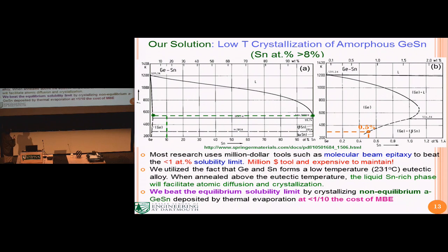And also, you worry about this equilibrium solubility limit. If you want to break those kinds of limits, you should enter a regime where the basic assumption of this phase diagram doesn't hold. All phase diagrams are based on the assumption of thermal equilibrium. If you go to a non-equilibrium state, then you have a chance to break that limit. So we actually beat this equilibrium solubility limit by crystallizing non-equilibrium amorphous germanium tin on dielectric layers and amorphous materials. We're doing this deposition by thermal evaporation, and that's less than 1/10 of the cost of MBE. So we achieve our goal, and we save Joe $2 million right there.